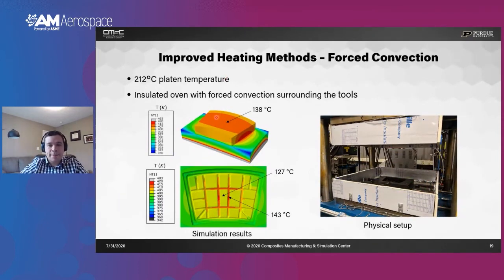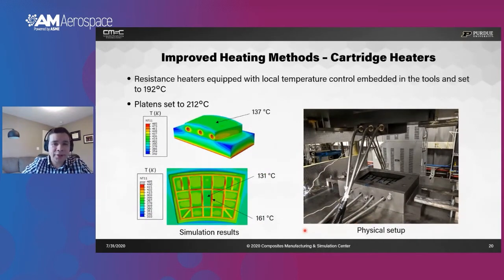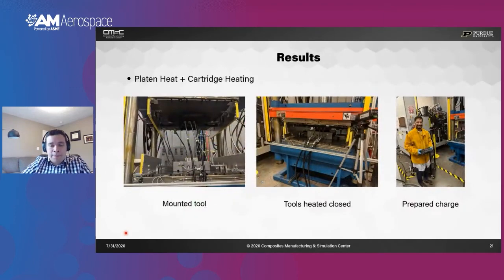Another option was enclosing the hot press and introducing forced convection conditions on the inside. By doing so, as you can clearly see here, we can reach higher temperatures. And a third consideration was inserting cartridge heaters with controlled temperature at each of those cartridge heaters. With this approach, which was the one finally implemented by Thermwood, we were able to reach processing temperatures that are closer to our target processing temperature of 150 Celsius. So that was the chosen solution: using the heat from the platens in the hot press plus the cartridge heating.